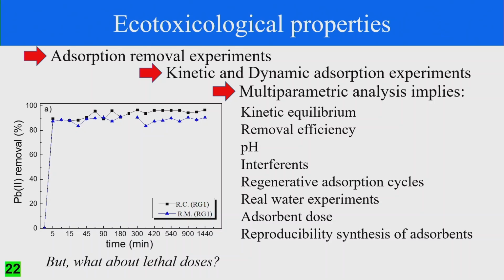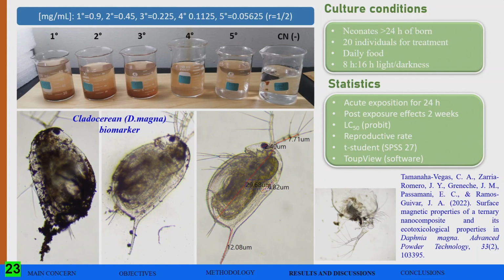Each nanoparticle has a different character, depending on the method, as you all know. So here we have a kinetic equilibrium time that we have found is at least 1 hour. The points are triplicates for each time. And we can see that only the maghemite nanoparticles can adsorb very well in real waters, where they have other competitive species that can affect the adsorption. It's a very good adsorption that can be improved using the zeolite. I'm not showing the zeolite here because of time, but the equilibrium time can be reduced to less than 1 hour. So, focusing on the lethal dose concentration, we have to apply that to an environmental biomarker.